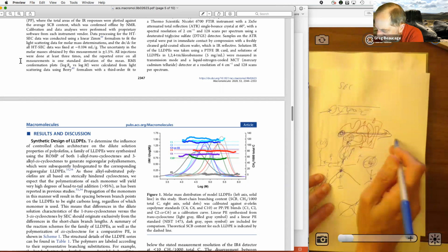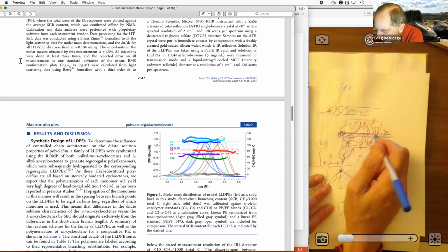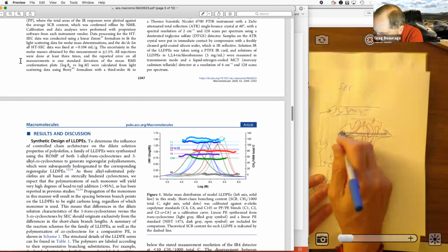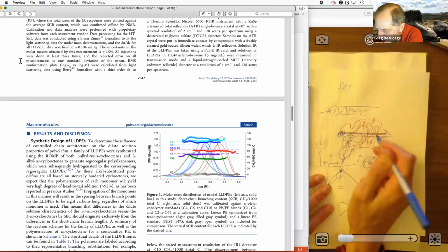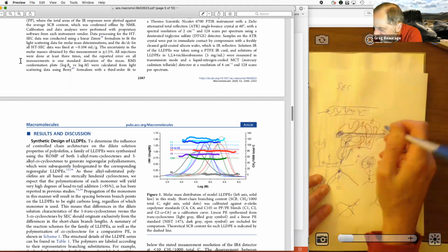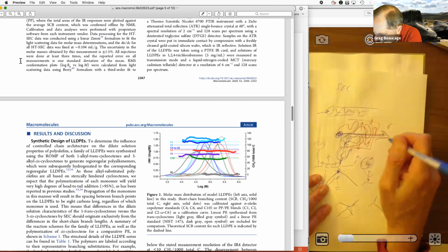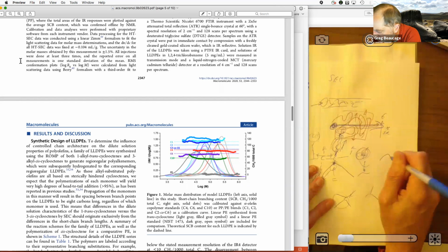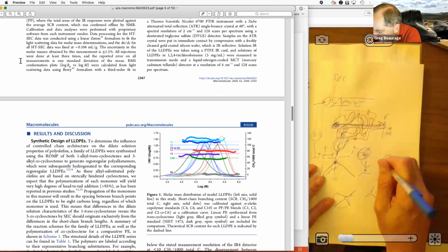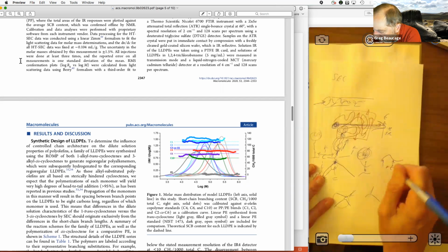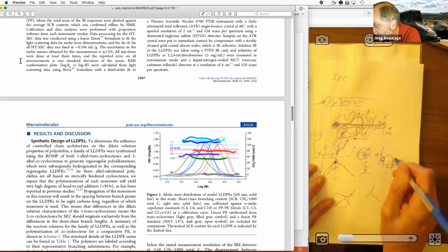Right, so one of them is going to have a diffusion path. The other, depending on the size of the thing, the smaller it is, the more that porosity it explores, so the longer it takes to get out. So if you measure the time of coming out, you have some kind of a detector here, like an IR detector, or an index refraction detector, then you can say, like, you're going to have a distribution curve, and the low molecular weight things are the shortest time. So this is retention time, and then this is whatever signal, like index refraction, proportional to concentration, and then the short things are coming out first, and the big things are coming out last.